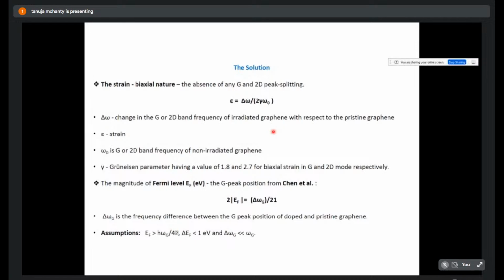And what we find, I can say that we have an absence of any G and 2D peak. First, we find a strain. So what is this strain? Strain is the variation in the Raman peak, if there is a variation in the G and 2D peak, so here the strain is there. So strain is calculated as the change in the G or 2D band frequency of irradiated graphene with respect to the pristine graphene. So Raman peaks naturally correlate with, if you insert a series of defects inside the material, naturally a strain will be induced in the material.